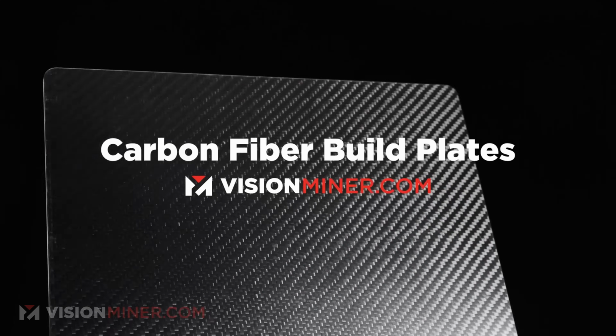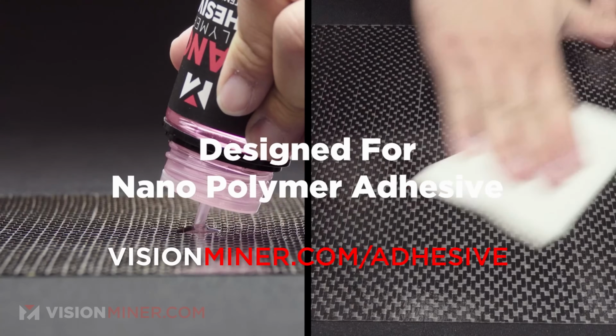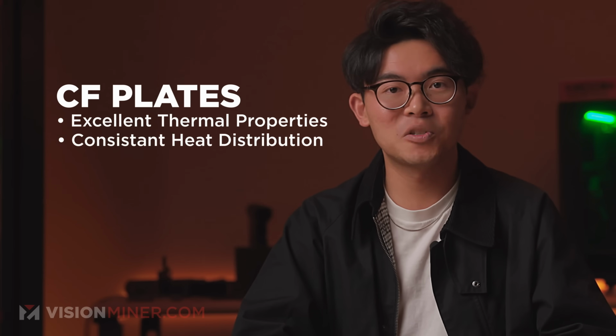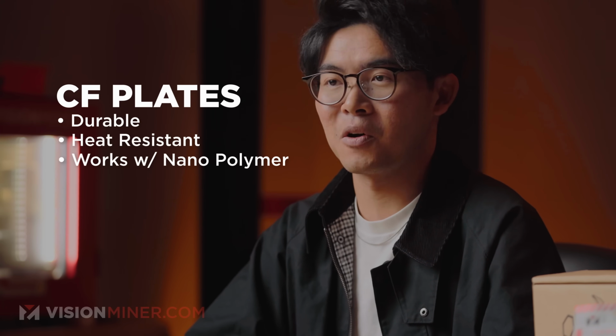We recommend using a carbon fiber build plate alongside Vision Miner's nanopolymer adhesive. Carbon fiber build plates offer excellent thermal properties, maintaining consistent heat distribution and making it easier to remove prints without damaging the surface. In our early days, we were breaking several glass build plates a day, printing high-temp materials like CF PEEK. Carbon fiber plates are durable, heat resistant, and work exceptionally well with our adhesive.